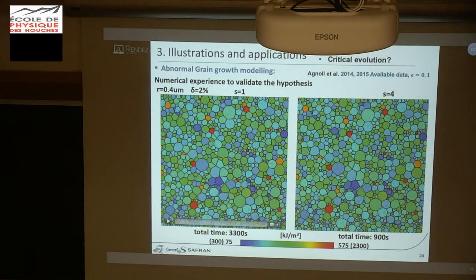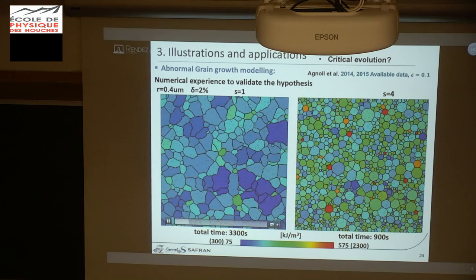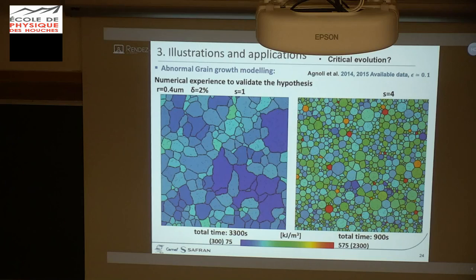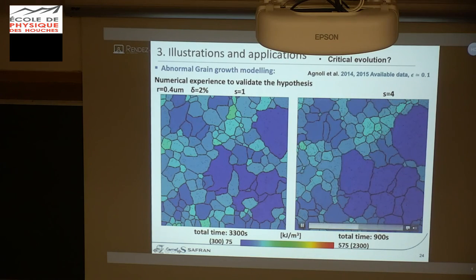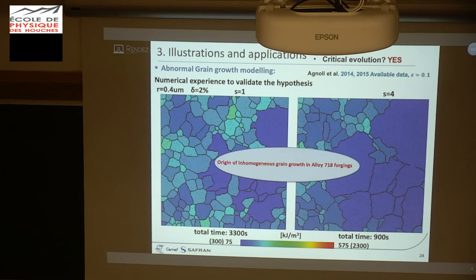With this kind of simulation, to do a summary, on the left side you can see thermal treatment where you don't have stored energy, but only growth due to capillarity and pinning due to the presence of second phase particles. And on the right side, you can see the same evolution, but with small residual amounts of stored energy due to non-fully recrystallized grain. And what you can see with the full field simulation is effectively the appearance of abnormal grains comparatively to the other simulation.